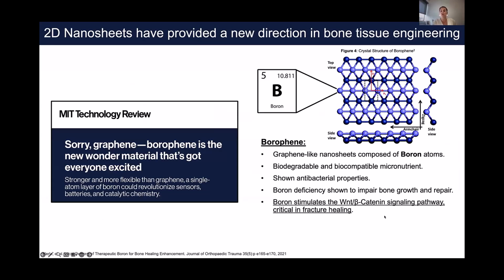So it's biodegradable. So given the impact of this boron on the osteogenic response that we saw in the previous study, and we knew as well that boron deficiency shows impaired bone growth and repair, we thought, oh, maybe we could produce that borophene, dope it with cement, and get even better results than this injection of boric acid. Okay. So that's what we did.